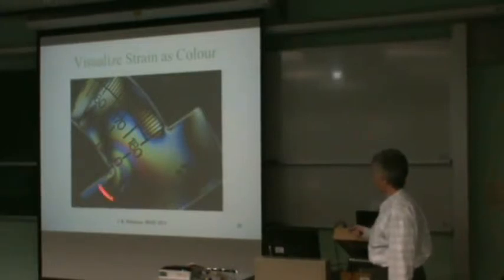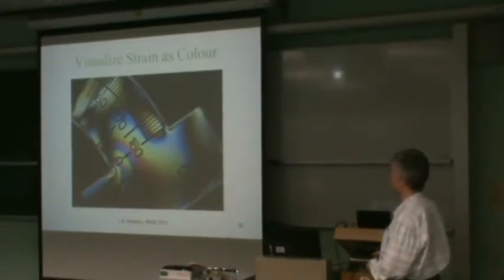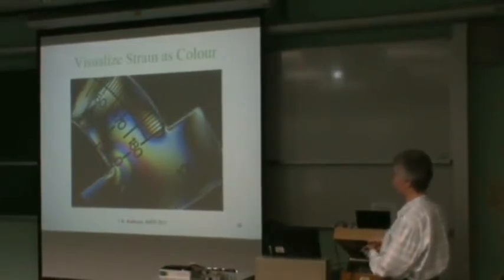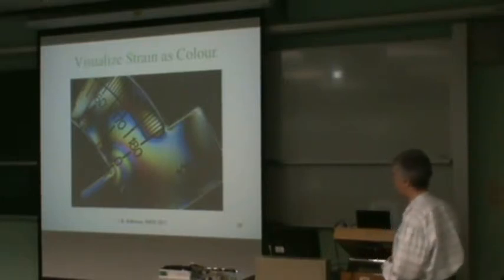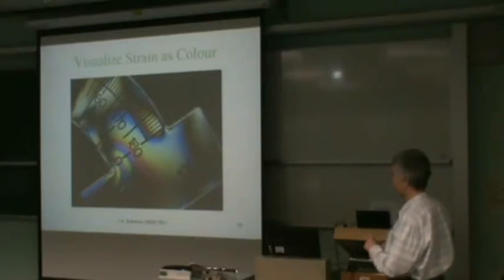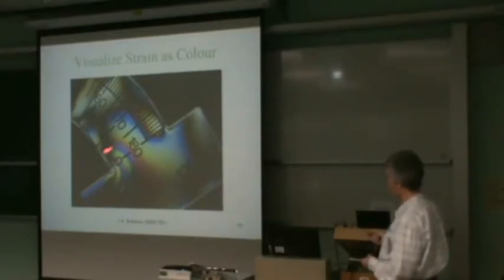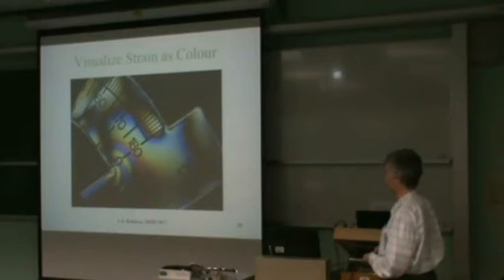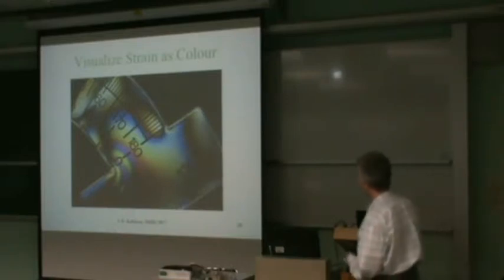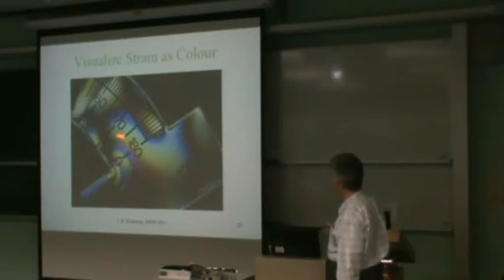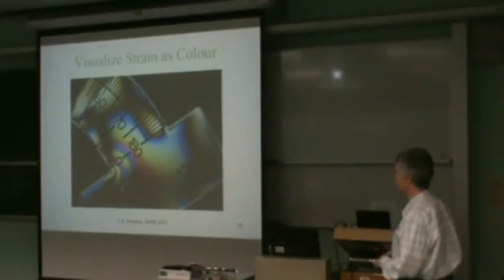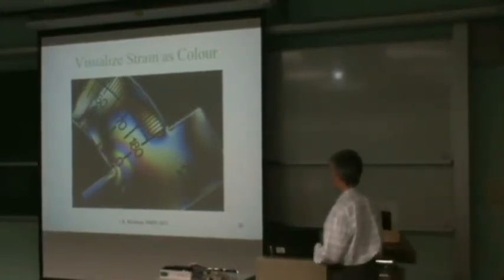Anyway, so what we are able to do then is to get a color image of the distortions of the material, and it's completely unrelated to this method here, which is polarized light, visible light microscopy. But it does make the very important point, which we will see later on, that the strain gets concentrated at corners in the structure, and we saw a nice example of that from the previous talk. But it also makes the point that the strains are relatively slow varying. So the idea that you have 20 nanometer spatial resolution for distortions which correspond to picometer level changes in the crystal is actually quite appropriate.